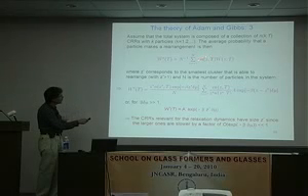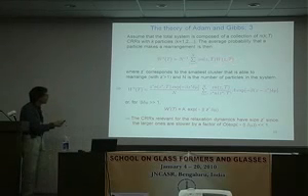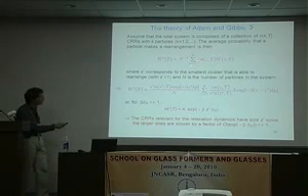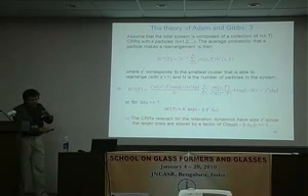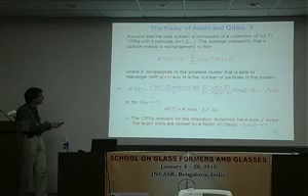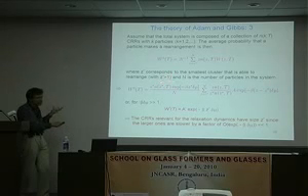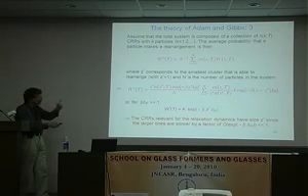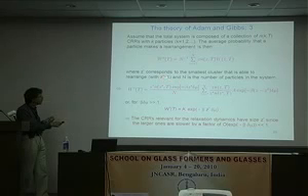So that's the total number of particles in a region of size Z, times the probability that such a region really flips. Okay? And here the sum starts not at 1, but at Z star, which will later become a fit parameter, and which corresponds to the smallest cluster that can actually do something. In the extreme case, Z is 2, because a cluster with one particle doesn't make sense to say it's jumping. So Z star is certainly larger than 1, but what it is we will see later on.